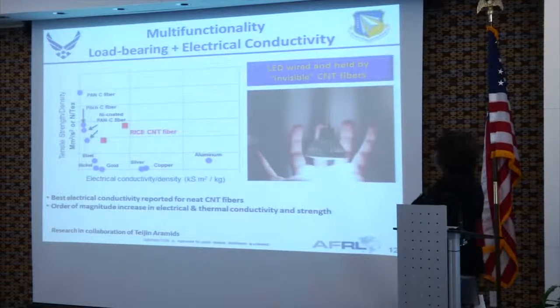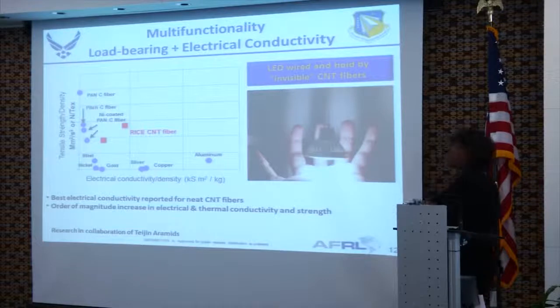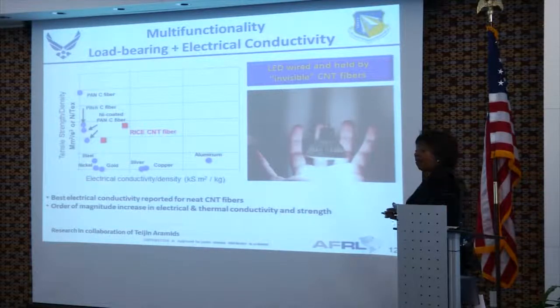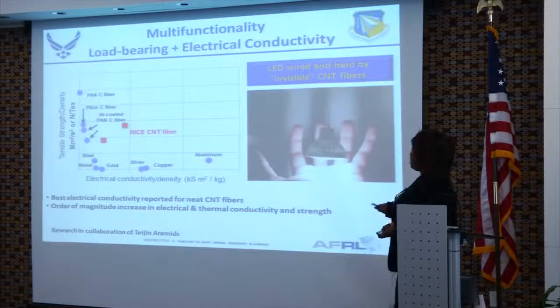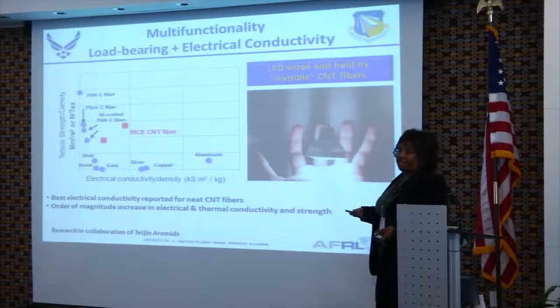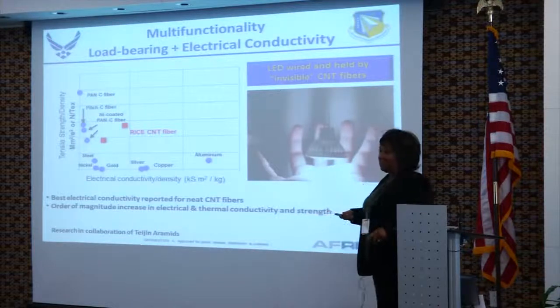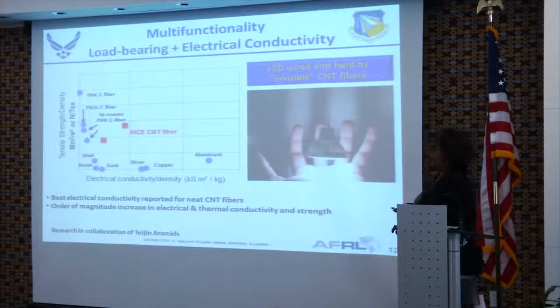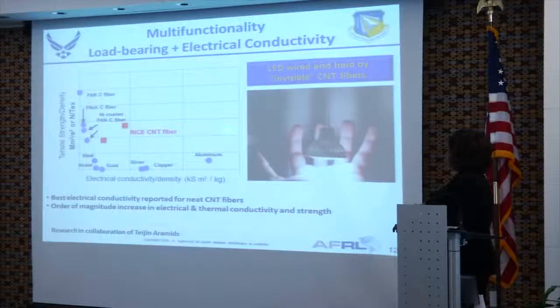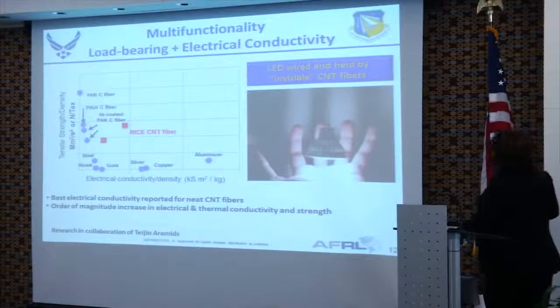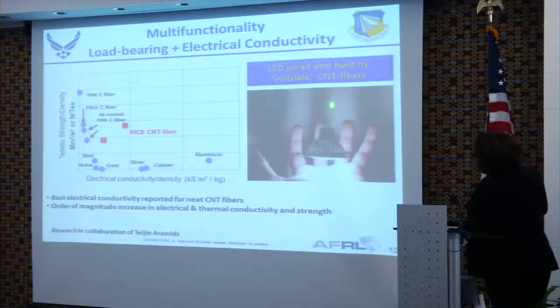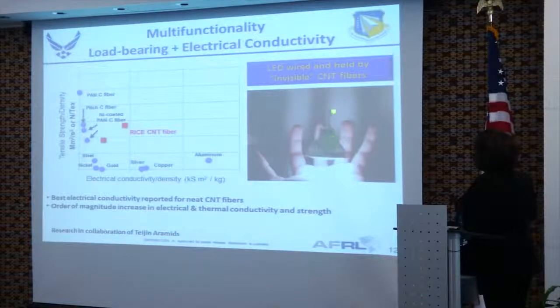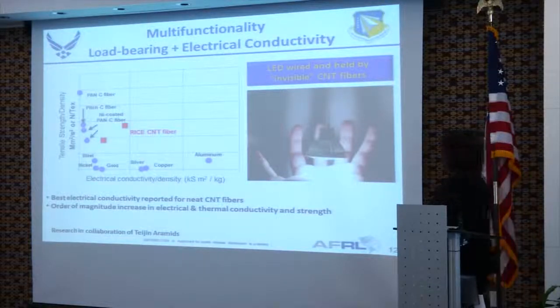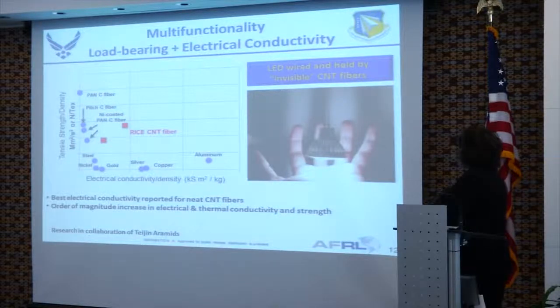just last week I got a string of excited emails, a lot of buzz, because the folks at RX at Wright-Patterson have begun to do measurements of the thermal conductivity of these materials, and the thermal conductivity numbers are really, really high. So they were very excited about the early measurements of also thermal conductivity in these structural fibers. And this picture here is a picture where they have it's hard to see, they call it invisible, but this LED is being held up and wired by one of these carbon nanotube fibers.